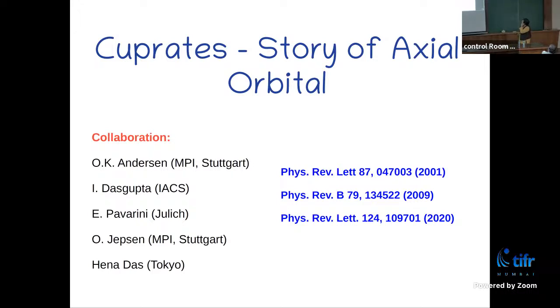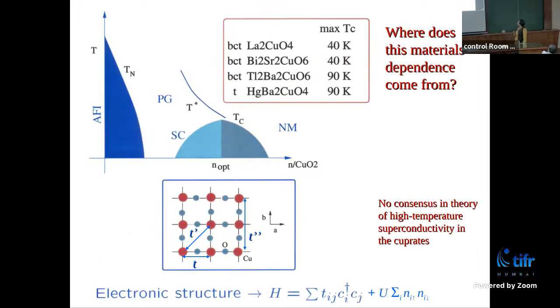And the story we had is that of an axial orbital. So this is a cuprate phase diagram. I think many of you know this phase diagram. This is basically temperature versus doping, with hole doping at the copper oxide plane. In the undoped situation, you have an antiferromagnetic insulator. By doping, beyond a certain doping, superconductivity shows up and it has a dome-like shape, with the maximum point of this dome being the TC at optimal doping.